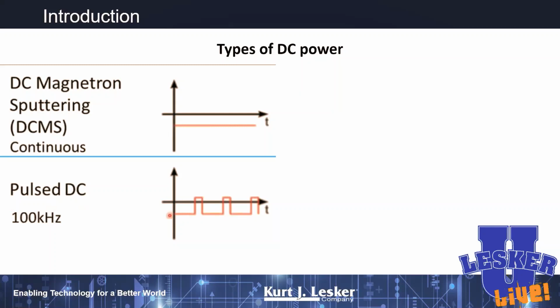In this case, we're going to give our target a negative pulse, and then we're going to give it a little bit of a positive pulse in order to relieve any of these positive ions that may have become embedded in our weakly conductive target. And this is also pretty handy for reactive sputtering. This positive pulse tends to clean away some of the redeposition of, let's say, a nitride material that might be showing up on our titanium metal target.